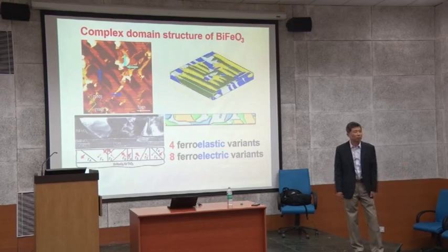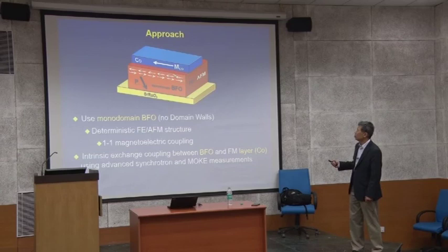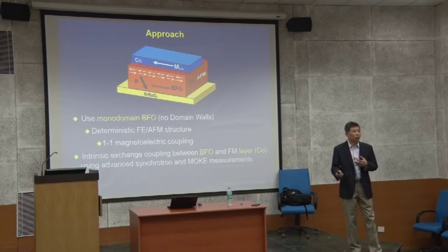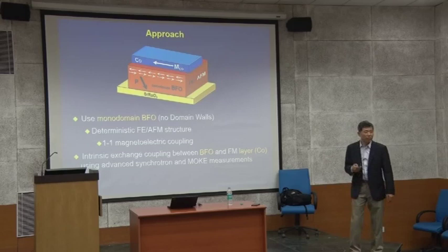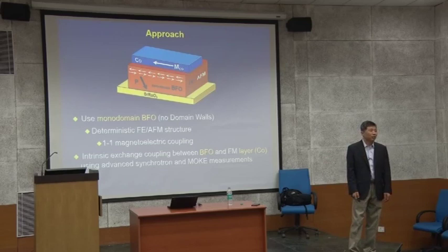Then ideally, you want this. Can you get rid of all the domain walls, make a single monodomain bismuth ferrite, no domain walls? That means all the switching is deterministic, and then we can study the intrinsic exchange coupling between bismuth ferrite and the ferromagnetic layer, and use other characterization techniques, synchrotron-based PEEM measurement, and MOKE measurement. You don't have to worry about different regions and domain wall contribution. This is a very simple approach everybody can think of, and how can you do that? That's something you want to do.